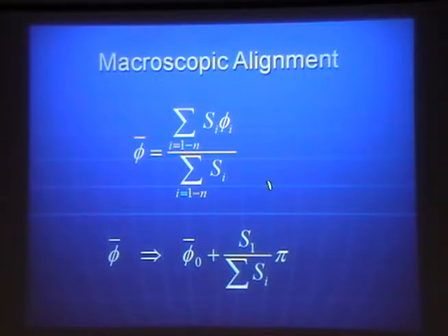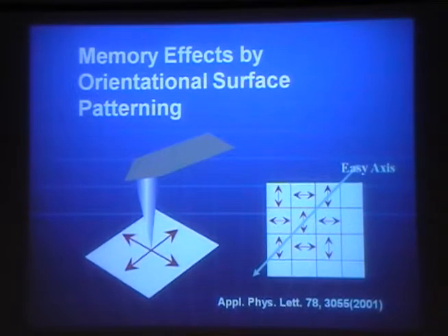So once again, the total average orientation that you can achieve when the position is just a little bit away from the surface is an average of the surface orientation with the weight of area. And so in this case, you have equal area of horizontal or parallel orientation and the same area of vertical orientation. So taking the average, what you get is 45 degrees.